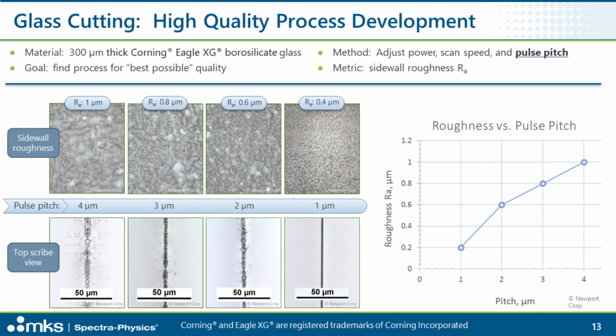Of course, there are other parameters other than the beam intensity distribution, such as the spacing of the pulses in the material and the number of pulses as well. Here we have a development demonstration for optimizing the spacing of the pulses in the material for creating the highest quality glass cut. In the top row of microscope photos, we see the sidewall cross-section for a pulse pitch going from 4 to 3 and so on down to 1 micron spacing on the material. The spacing is adjusted by changing a combination of either the scanning speed or the pulse repetition rate or both.